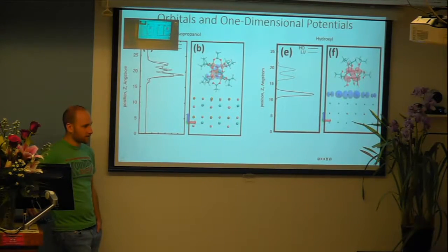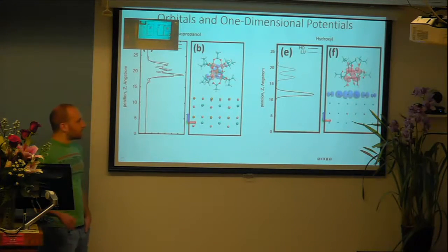I don't understand your definition of a charge transfer. What's the purpose of this? This charge transfer state will not provide you any good things for the current. Because your idea is that this construction of the material is based on using one as the absorption material, the sensitizer, and the other would be your contacts. And it looks like probably the two-dimensional surface would be your contact, right?